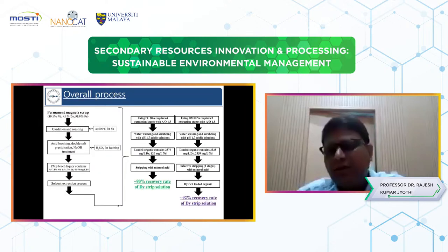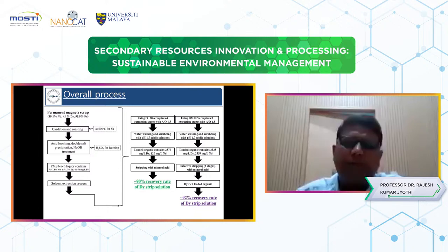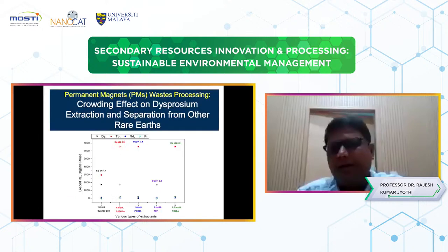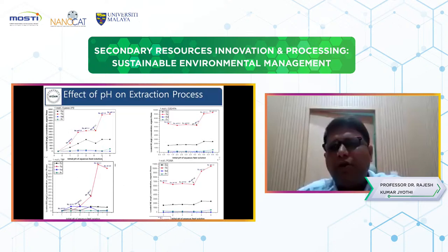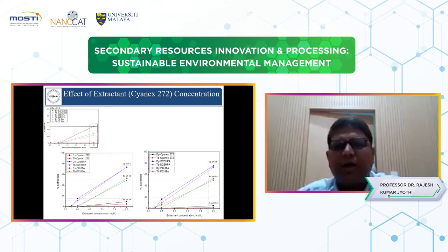So in this environmentally friendly methodology, we can recover more than 90% of the rare earth metals from waste permanent magnets. After that, we have one unique characteristic, a crowding effect. For another material containing dysprosium and terbium, we tested the crowding phenomenon to replace the terbium with the dysprosium and make a maximum dysprosium recovery. It was successful, and we published this data in Separation and Purification Technology and Organic Analysis.